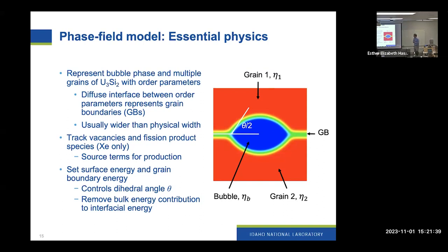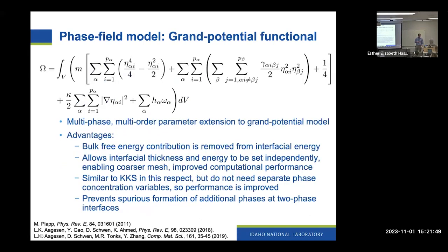So in order to parameterize this model, it would be nice if we could remove the bulk energy contribution to the interfacial energy between those phases. So to do that, for this work and for several of the other projects that I'll describe, we're using a model that we developed a few years ago based on a grand potential functional. So historically, most phase field models have been based on a functional of the Helmholtz or the Gibbs free energy. Then Plapp showed a few years ago that there are some advantages to using the grand potential as your thermodynamic variable. And so we developed a multi-phase, multi-order parameter extension to the grand potential approach.